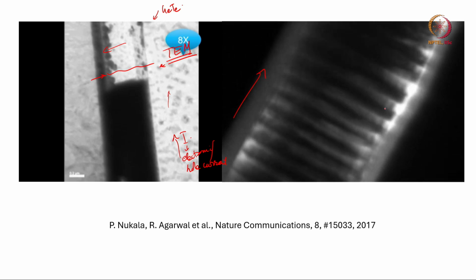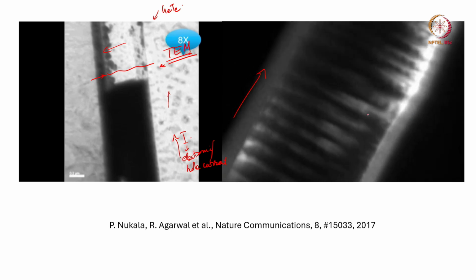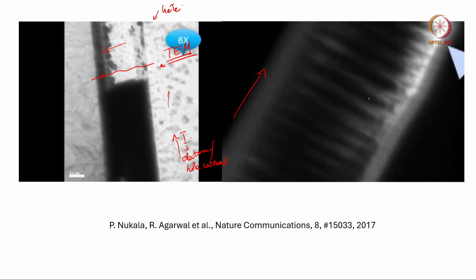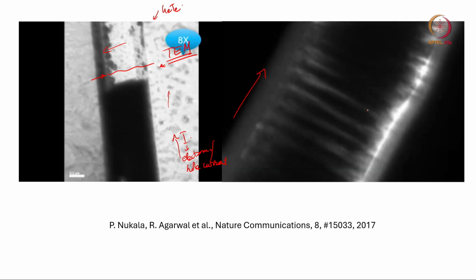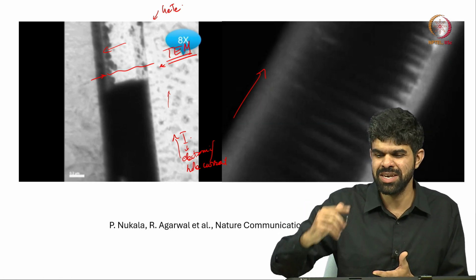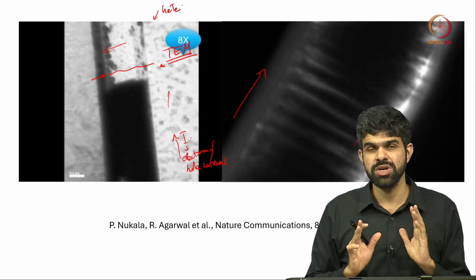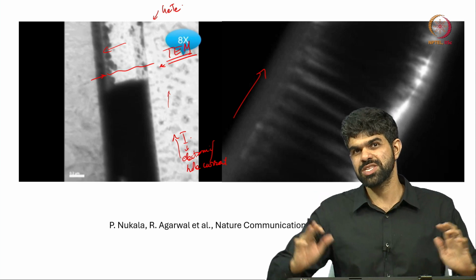And you can actually see that there is some mass motion, right. So with current moving in this direction, you can see there is reorganization of all these things, there is some sort of a motion in general, right. So this is a very controlled form of atomic motion, if you will. Okay. And something else happens, we do not worry too much about what happens there, but you can see all these defects sort of moving in an organized fashion in this direction, right. So along with the electric wind force, along with the carrier wind force, the defects are also moving, right.